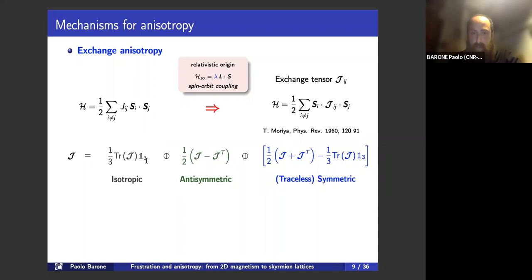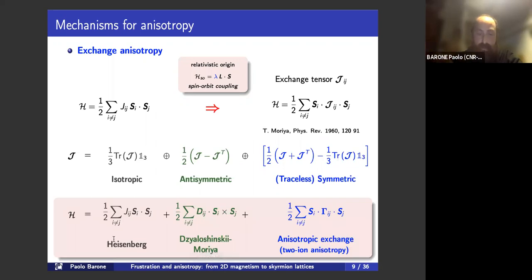First one is simply the trace of the tensor, which is isotropic. And then we have these 2 combinations. One is the antisymmetric and the other one is the symmetric combination that is taken to be traceless in order to have this isotropic term here. And this corresponds exactly to the standard Heisenberg isotropic model. The antisymmetric part actually corresponds to the Dzyaloshinskii-Moriya interaction. Moriya, when he derived this expression from the general superexchange theory, actually started from this antisymmetric decomposition and then rewrote this in the form that had been proposed a couple of years before by Dzyaloshinskii.